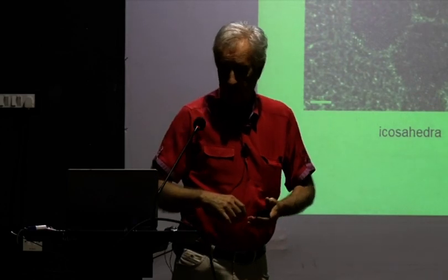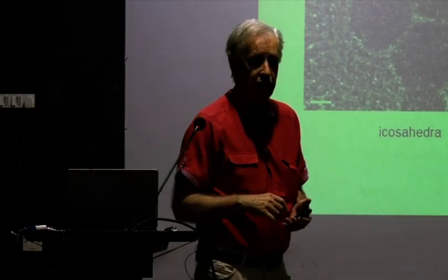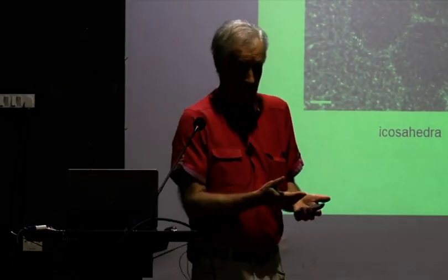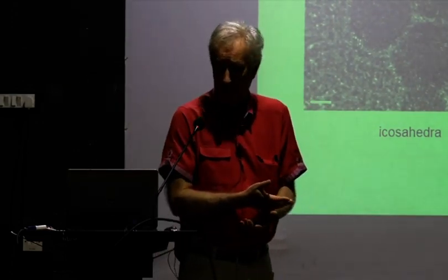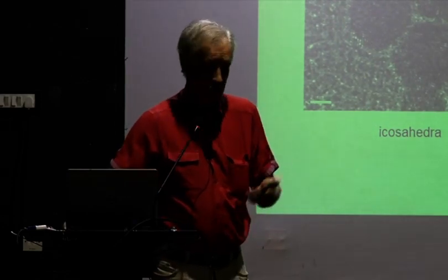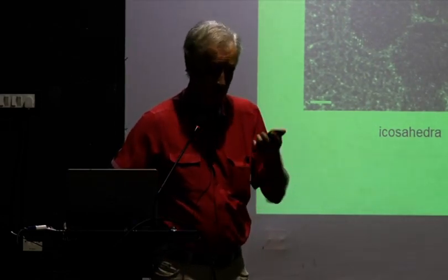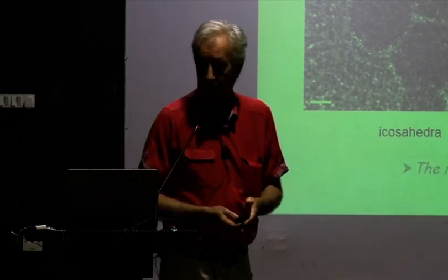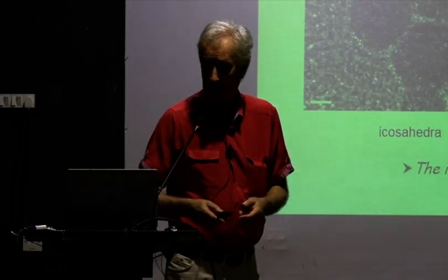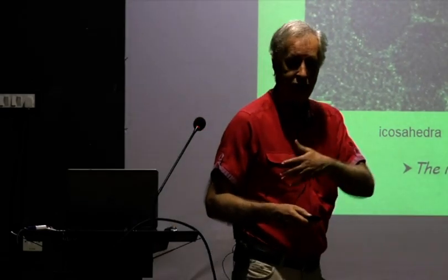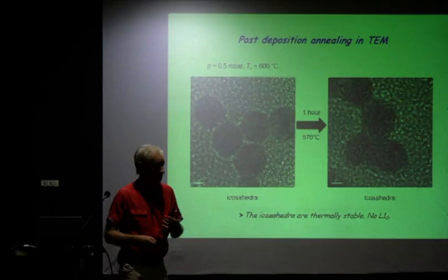We also took these particles and said, well, why don't we do post-deposition annealing on these things and see what happens. These are icosahedral particles. We took them to a high temperature, where they should transform into an L10 state, and we sat there for about 1 hour, and we see that nothing happens. It's quite interesting. This was the interesting thing that started coming out.